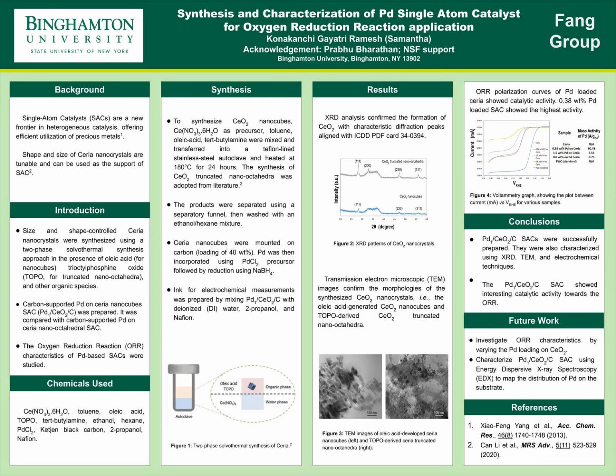So going on to the synthesis. The synthesis, as I mentioned earlier, is basically a two-phase solvothermal process as represented in Figure 1. In order to synthesize nanocubes, we use a mixture of cerium nitrate hexahydrate, toluene, oleic acid, and tert-butylamine, which were then heated in a Teflon-lined stainless steel autoclave at 180 degrees Celsius for 24 hours.